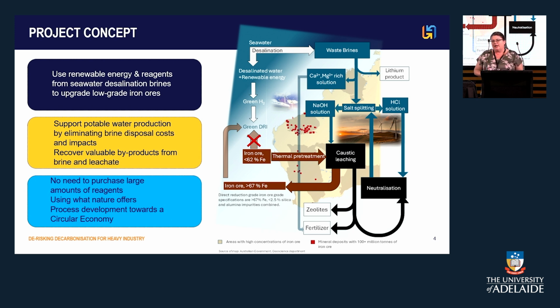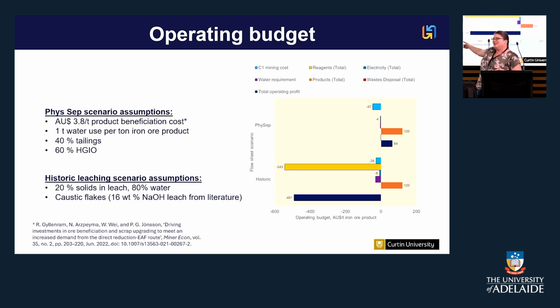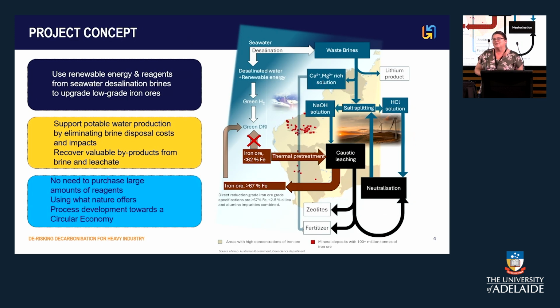So here you can see in our process we also have thermal pretreatment. Thermal pretreatment we think is crucial to open up that mineral structure with cracks, to give the leaching liquid more access to the impurities to dissolve them. And then when we do our caustic leaching, I should have said in the previous slide, this was not including the neutralization of the caustic waste. So definitely it wasn't going to work. But we neutralize our caustic waste with the acid that we've produced, generating again a brine.